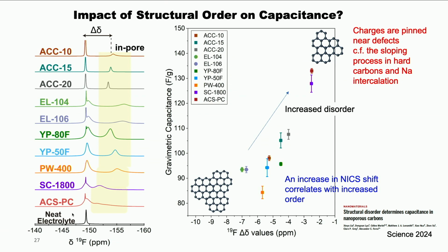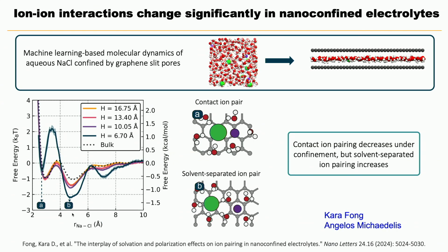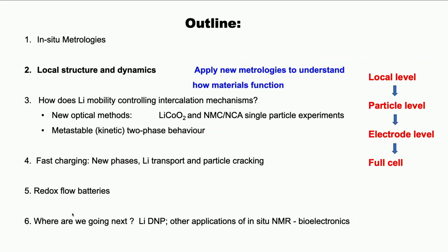And that's because if you have lots of defects in the carbon sheets, you start pinning charge near these defects, and then you can pin the ions nearby. This was a paper just published very recently. And then Kara Fong, who is a postdoc in my lab with Angelos Michaelides, has been doing some very beautiful MD simulations using machine-learned force fields to really understand the nature of ion pairing in these types of related systems. Okay, so that's my introduction on in-situ metrologies.